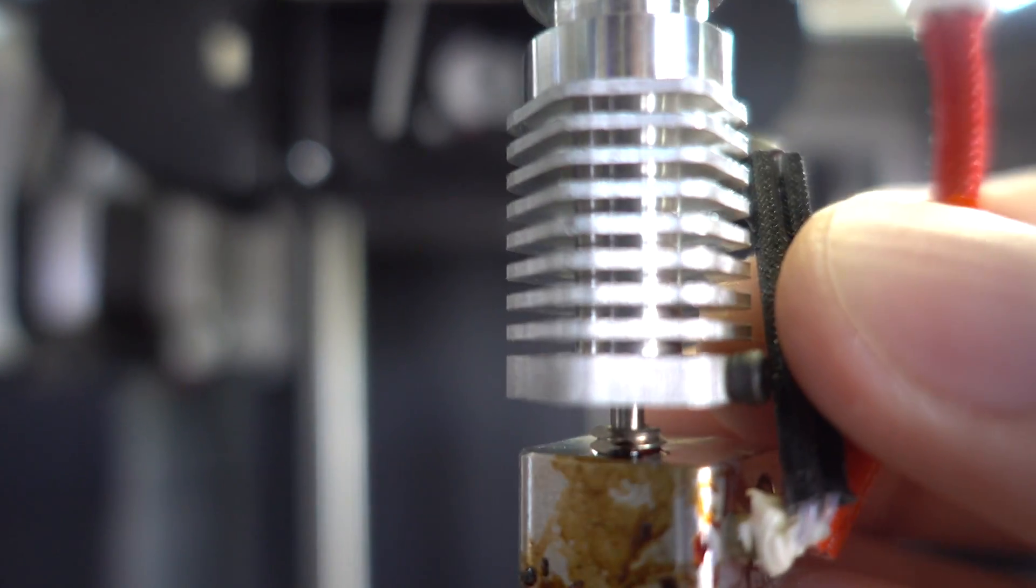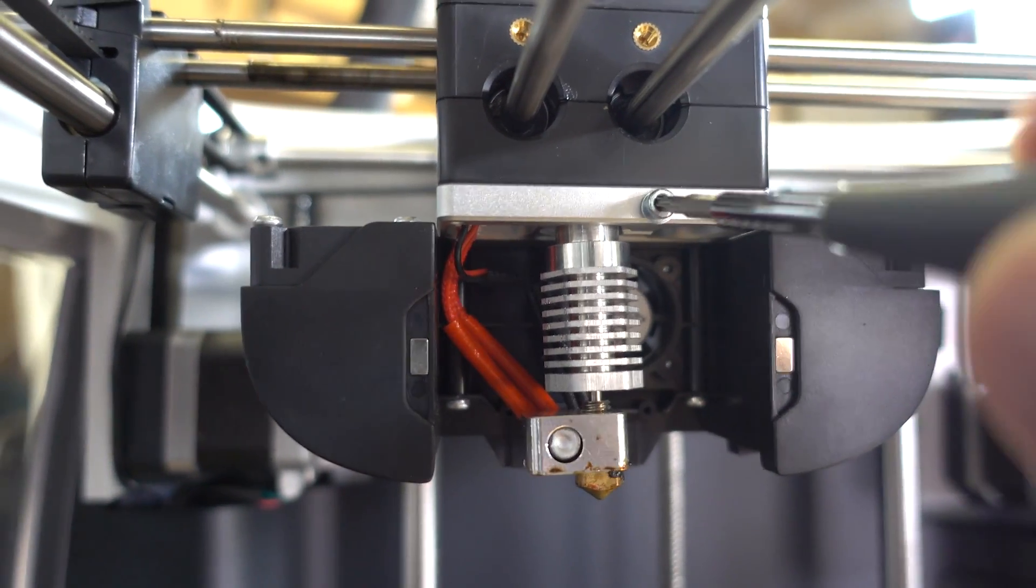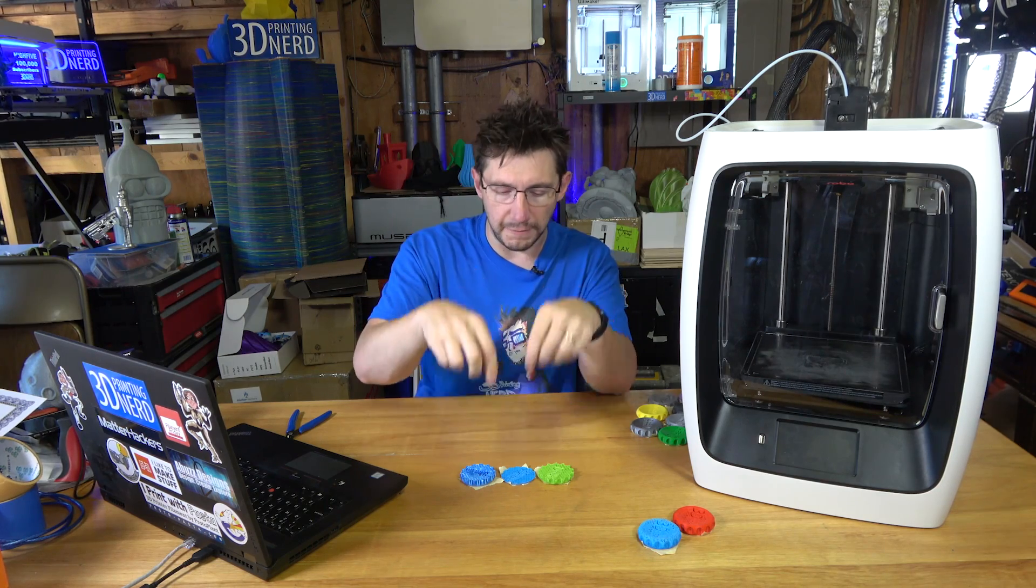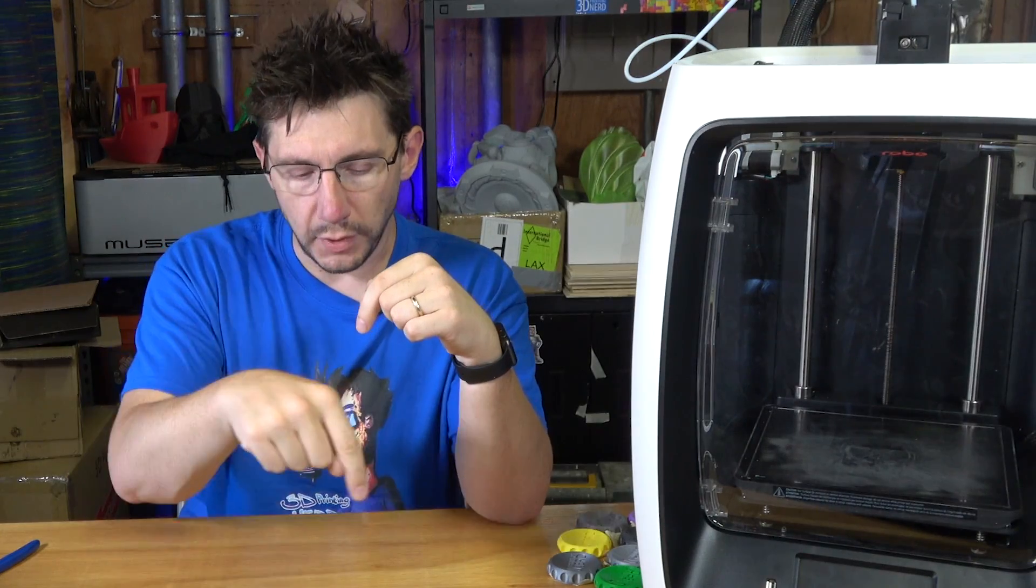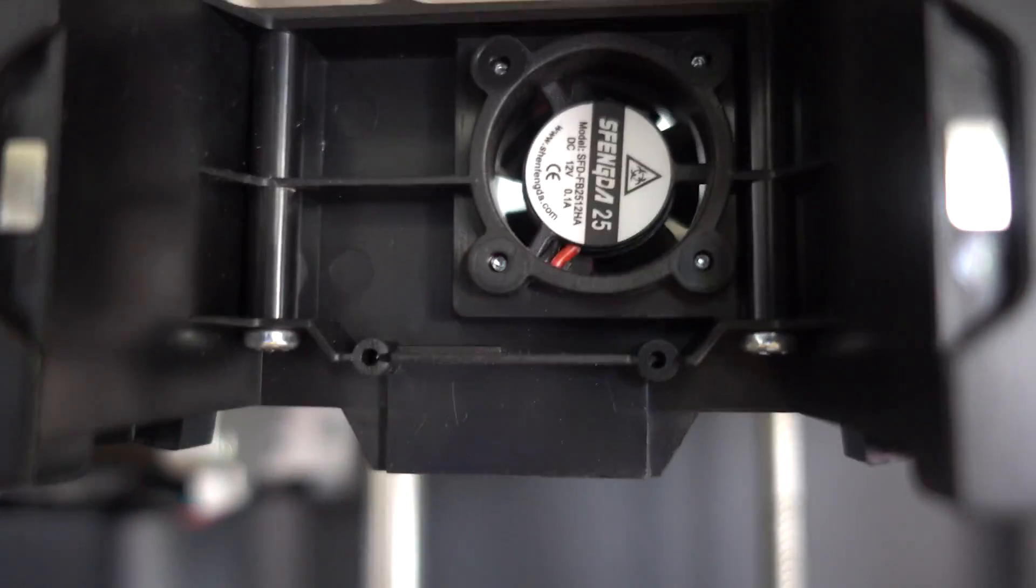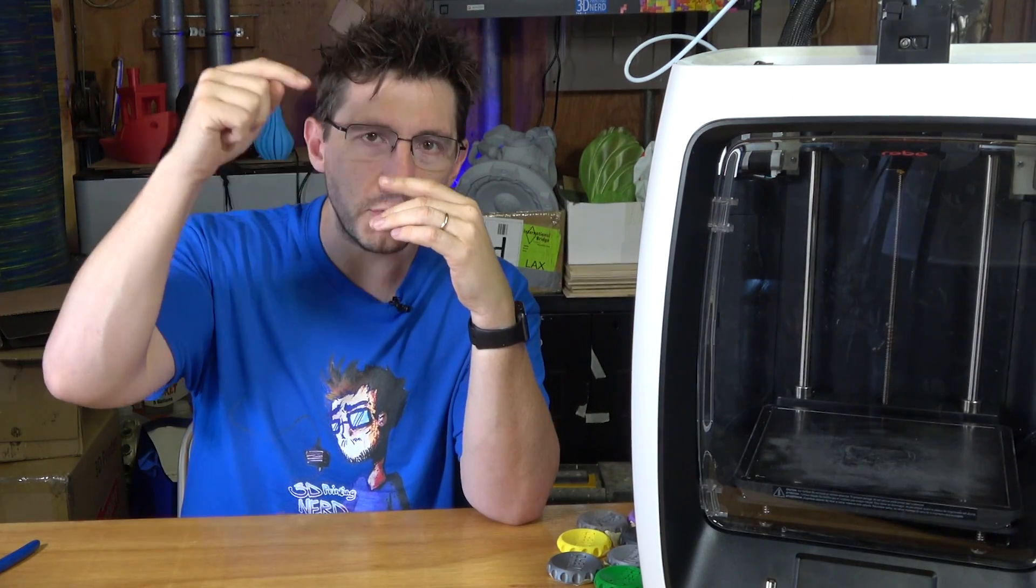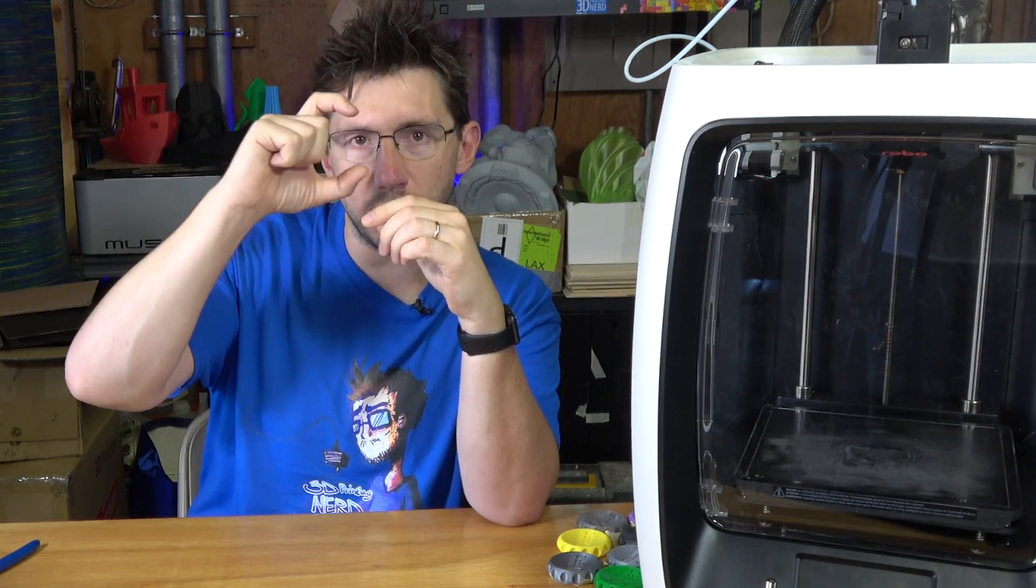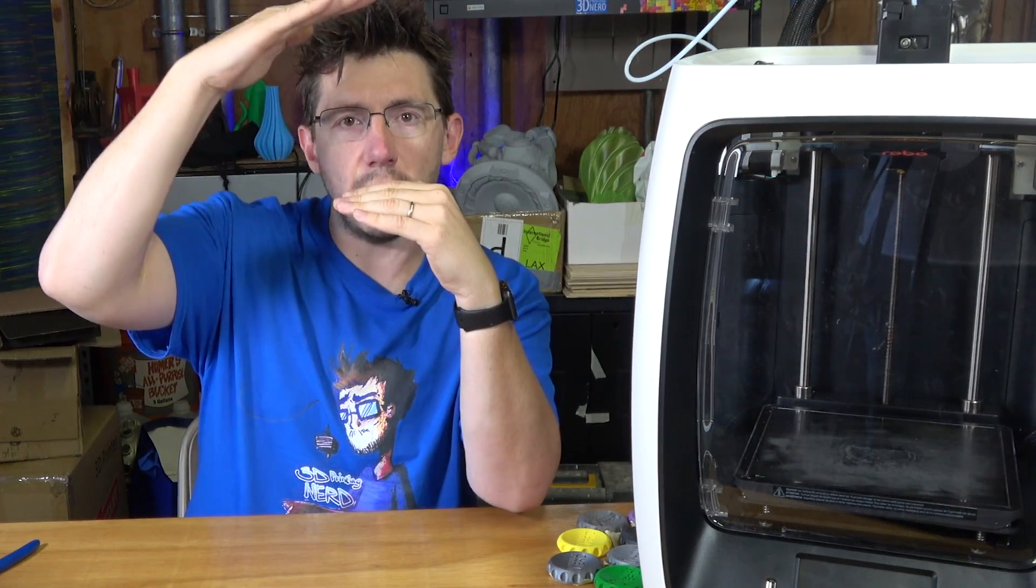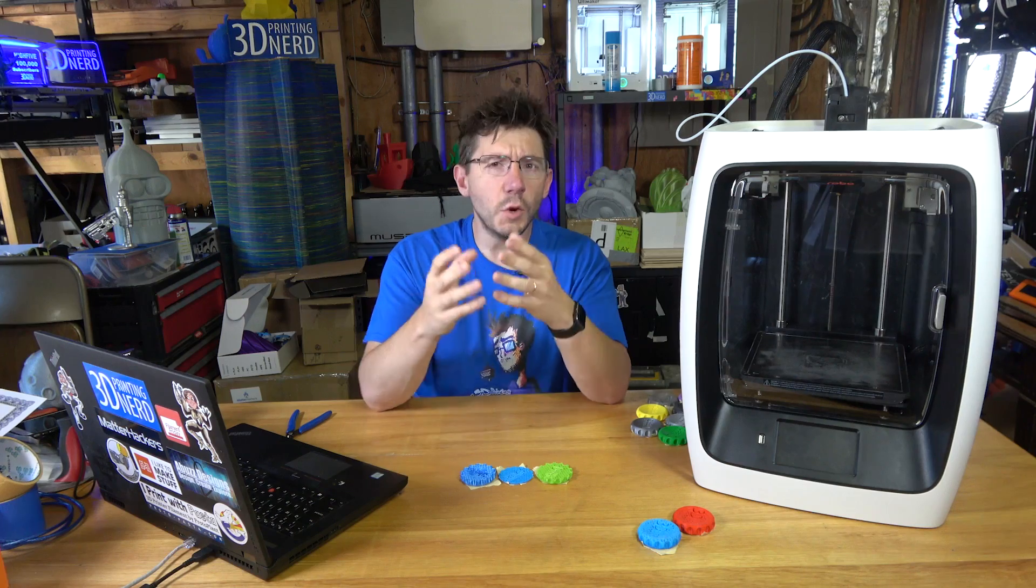The reason they failed is because something got blocked in the path of the filament going through from the extruder to the nozzle, and I think I know what happened. So as you can see, there's a nozzle heater block, a throat with fins, and then the top mounting point. If you undo this little screw right there, you can take this out and you can see. So at the top of the throat, there was always a plug of filament in the case of these three. And I think the reason they failed is during points in the print where it was doing a bunch of retractions, the fan in the back couldn't cool the fins fast enough to keep heat creep from affecting the filament. And the filament, when it was doing those retractions, essentially a piece of warm filament would come above the point of the throat at the top, and then the filament, when it was being pushed back down, it was soft and it would create that plug, essentially blocking the filament and not letting these prints continue.